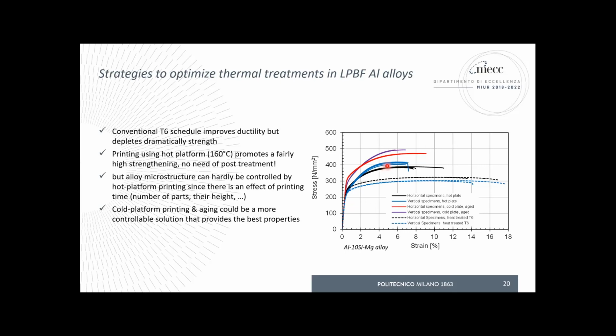But you can understand that we cannot control this process. Depending on the printing time, you can have underaged, peak aged, or overaged material, depending on how much the powder and the material is kept at high temperature. So it's not repeatable, I would say.